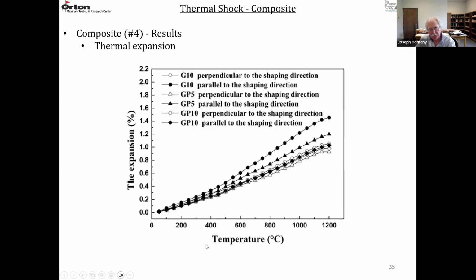So this is the thermal expansion that they measured versus temperature. And G10 is perpendicular to the shaping direction, and that's the open circle. And then this is G10, solid circle, parallel to the shaping direction. So when you press this material, the flake graphite tends to align, and the material is no longer isotropic, it's anisotropic. So the solid circle is parallel to the shaping direction, and then the open circle is perpendicular to the shaping direction, and that open circle is down here. So even as a function of direction in this one material G10, you can see there's a difference between these two graphs. There's a gap between the solid circles and the open circles.